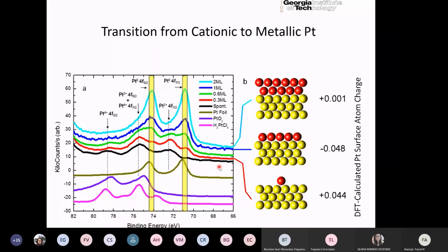Then we can see, if you're sitting with the microscope, that the energy from the electron gun of the microscope actually drives reaction. It drives a rearrangement of the platinum, and we can see, for example, here, as we sit there, we can watch the platinum atoms come in and form this film. And we can see platinum atoms migrating under different conditions here. And this is actually platinum atoms going across what looked like a thin layer of amorphous carbon. And at large enough thickness, when we start stacking up until we get the third layer, we start to see triangular arrangements start to emerge. Although they're not perfect triangles, we start to see this hexagonal arrangement, or kind of 1-1-1 type of reconstruction happening.